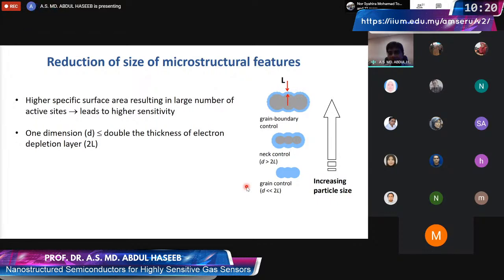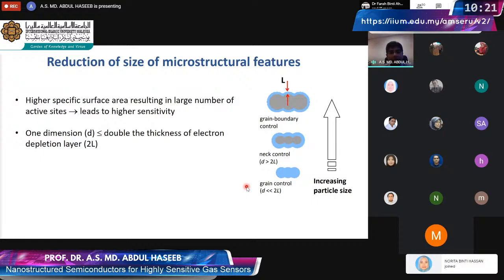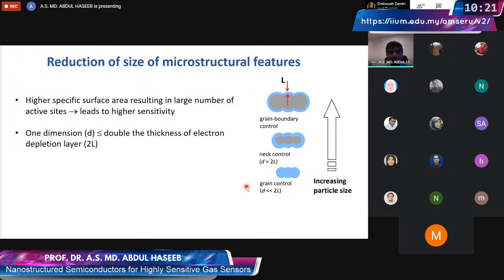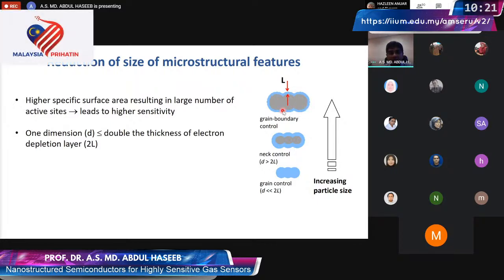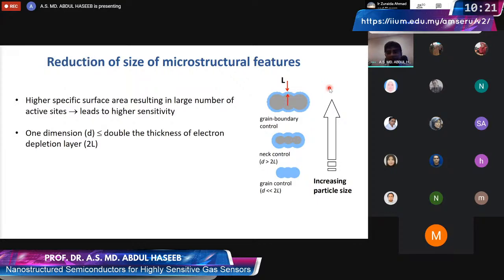Now, we know that we use material in polycrystalline state in the case of these semiconducting gas oxides. And when we use this material, the gas adsorption happens only on the surface in a very thin layer. And the rest of the material, gray ones, remain inactive or passive. Since a very tiny fraction of the material is active in gas sensing, that means that the signal that we get is not so strong.